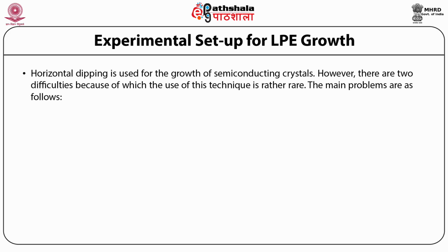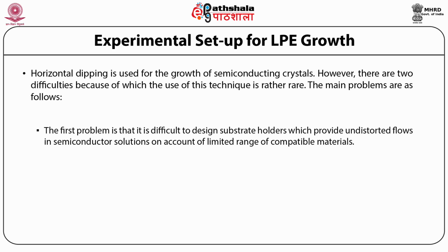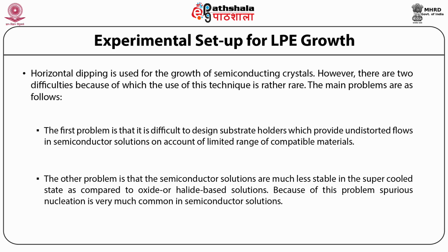However, there are two difficulties because of which the use of this technique is rather rare. The main problems are as follows. Number one, it is difficult to design substrate holders which provide undistorted flows in semiconductor solutions on account of the limited range of compatible materials. Number two, semiconductor solutions are much less stable in the supercooled state as compared to oxide or halide-based solutions. Because of this problem, spurious nucleation is very common in semiconductor solutions.